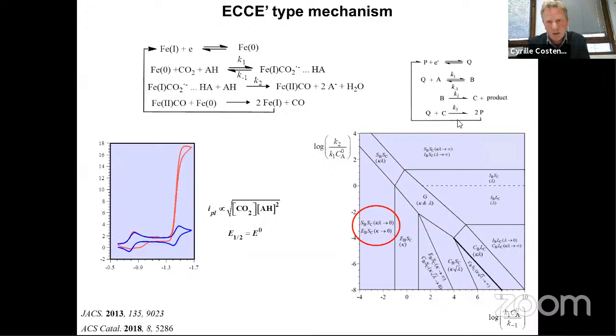So in that situation, if the homogeneous reduction is fast, then the system is governed by 3 rate constants, so 2 dimensionless parameters, and it's possible to show that there is only one zone in the zone diagram. Of course, I don't have time to describe how we construct the zone diagram, but there is only one zone that corresponds to the situation that you observe experimentally. And as I mentioned, here you can have 2 kinetic information actually.